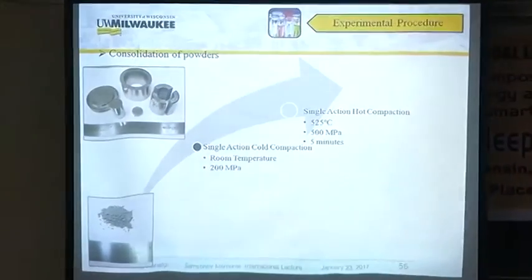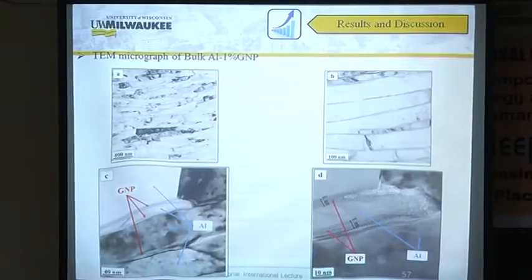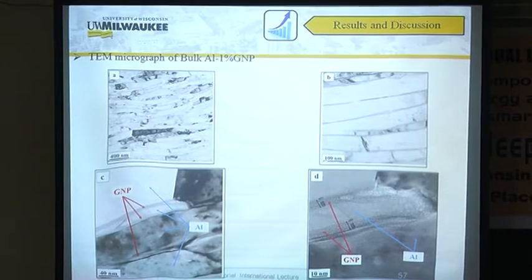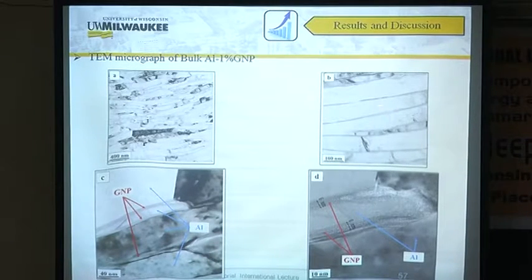This is a field that I've been trying to work on with Dr. Upadhyay. It's more powder metallurgy. And we are able to produce nanocomposites here. And this is the microstructure. See, this is the 100 nanometer scale. You are able to produce grains in aluminum that are nanometer size, and the graphene platelets are here. So you produced an aluminum graphene nanocomposite.